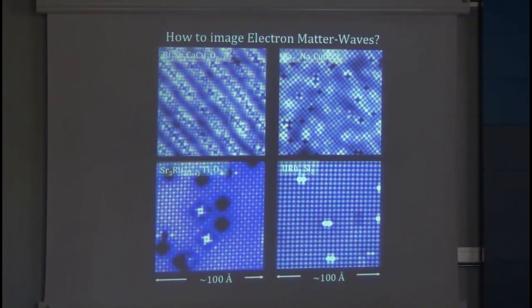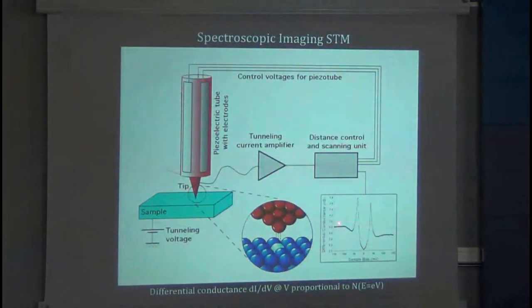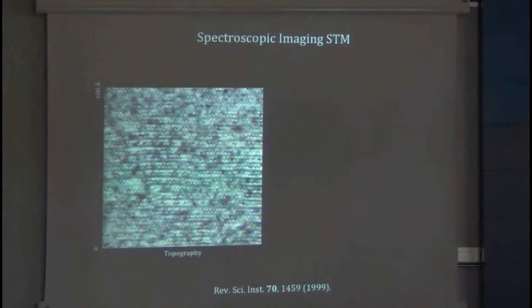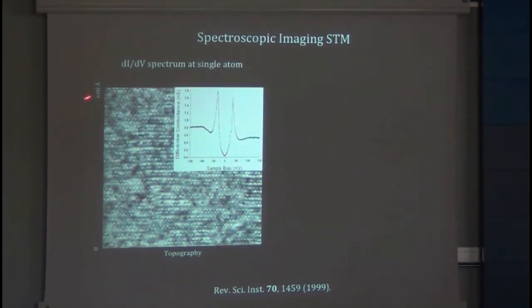To image the electronic matter waves, we use the technique where we stop the tip at every location and measure the differential tunneling conductance, dI/dV, as a function of the bias voltage between the tip and the sample. That function is proportional to the density of states. So here's the surface of high Tc superconductor BSCCO. There's about 30,000 atoms resolved in that field of view. And then we stop the tip at the first atom, measure the differential conductance, and the second atom, and the third atom, and so on, and so on, and so on.